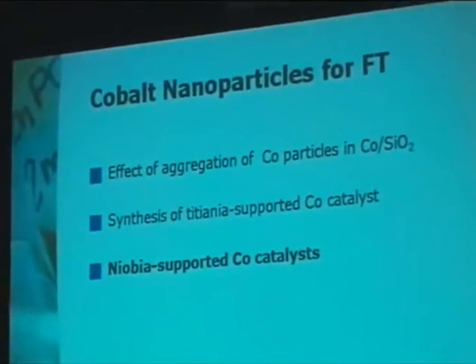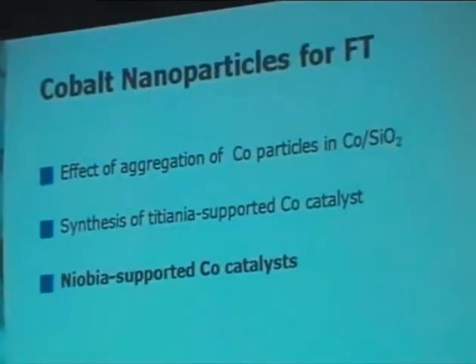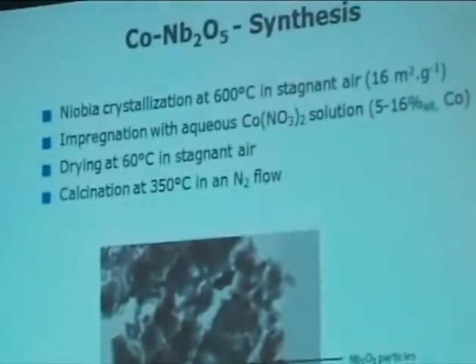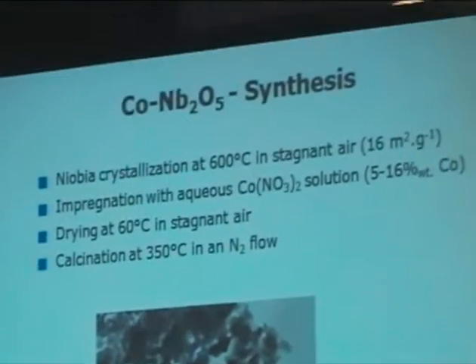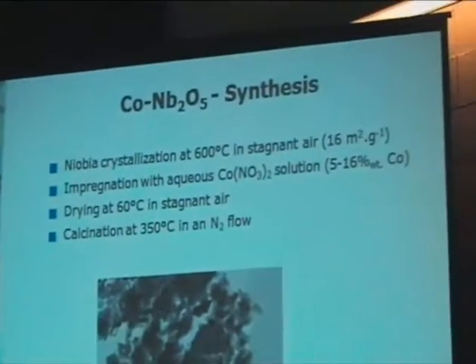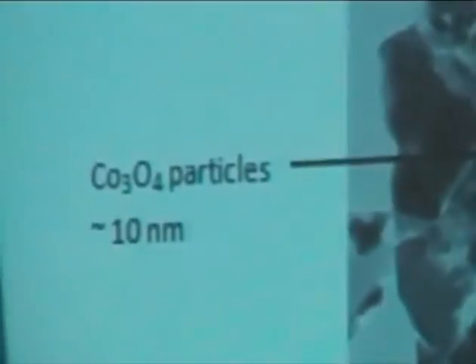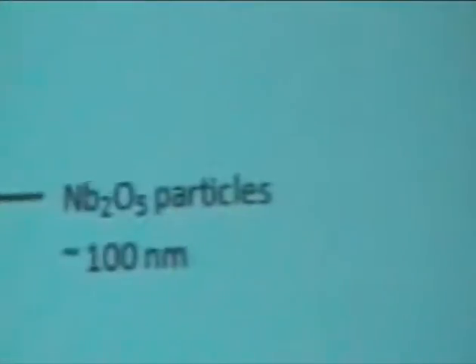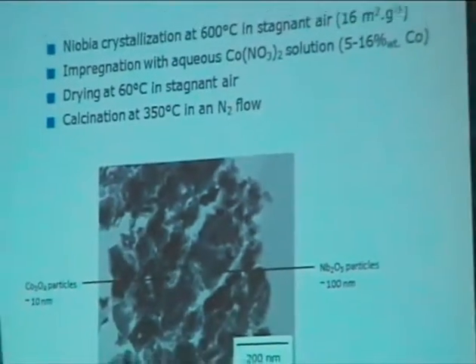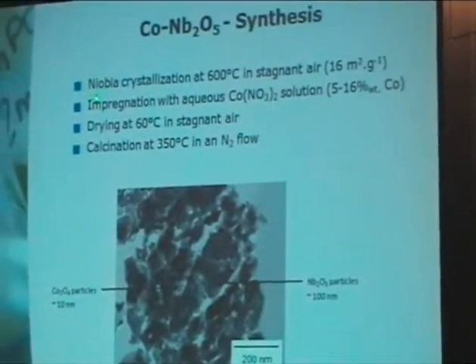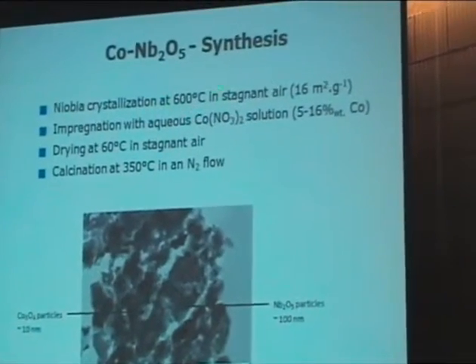Last topic for cobalt is niobium-supported cobalt catalyst. We had some interesting observations with niobium. It builds upon earlier work at University of Rio de Janeiro. Richard Small and others studied that quite some time ago to use niobium as a support, and they found that you need to have crystalline niobium. The amorphous niobium gives you low activities, so we followed that work and carried out the crystallization of niobium at